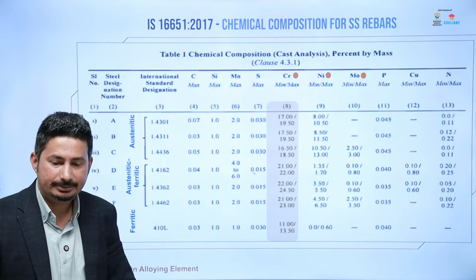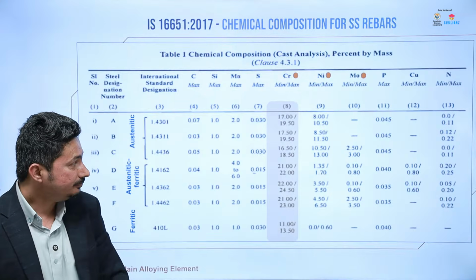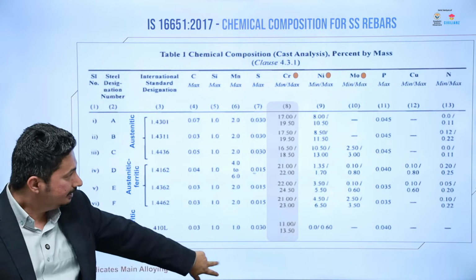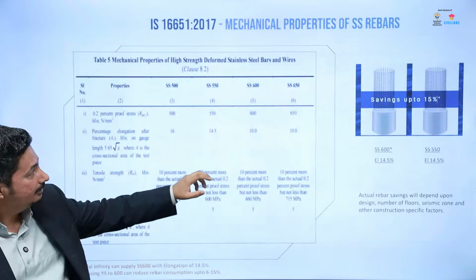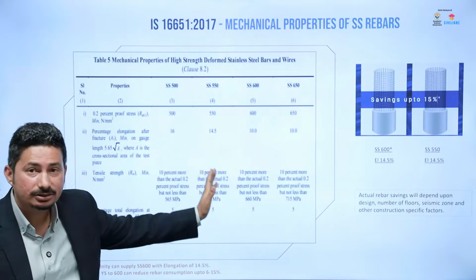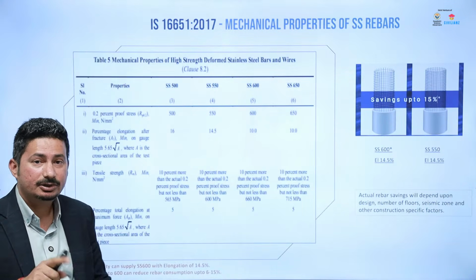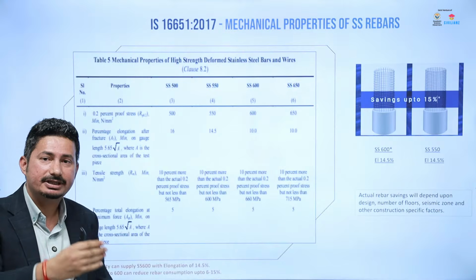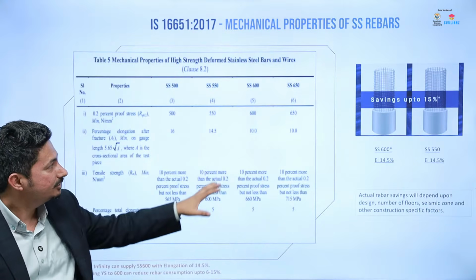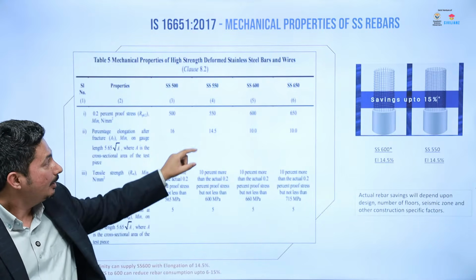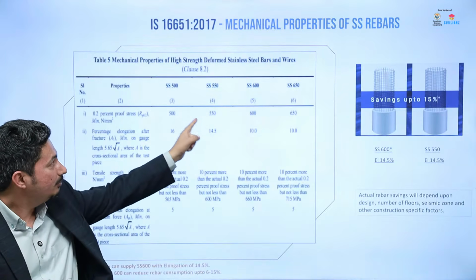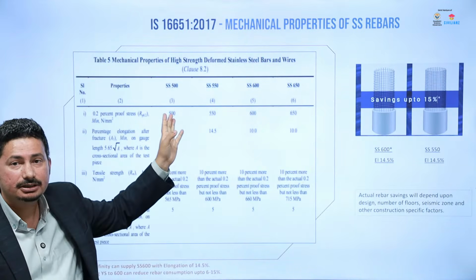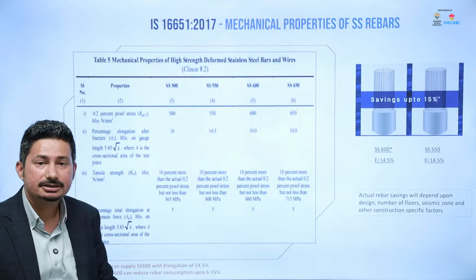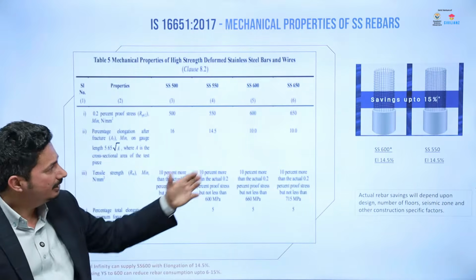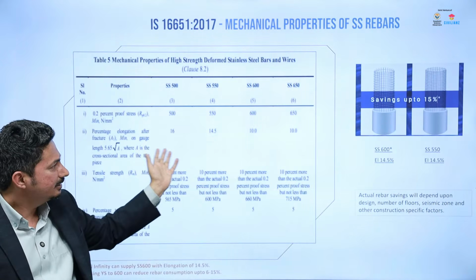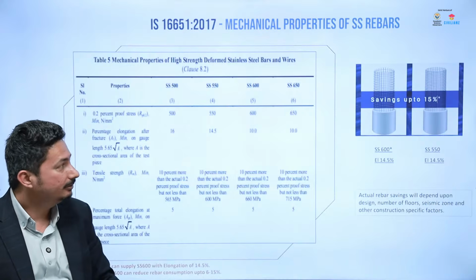Now, at the same time, this standard also defines the different strength levels of the stainless steel rebar. Remember, in TMT rebars, we have 500, 550, 600, 650 strengths. The same strengths are available in stainless steel rebar. Elongation of 14.5 with a combination of 550 is the most common combination that is being used across. In addition to that, 650 and 500, with 16 and 10% elongation, are also available.